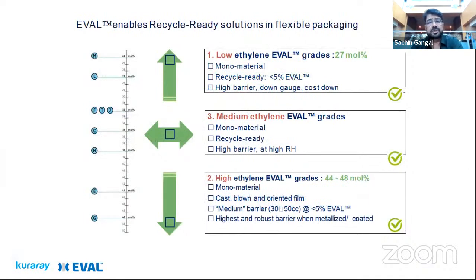We have several EVOH grades based on the ethylene content, where we have the lower ethylene content grades, which can be used to meet the new stringent regulations, where the barrier layer thickness has to be less than 5% of the total layer thickness. We have medium ethylene contents, where again, you require high barrier, probably at high relative humidity. Generally, they are used in combination with, not exactly recycling issue, but in combination with nylon, mainly for meat packaging. You have high ethylene content grades, which are used, as I said, in BOPP structures to give a robust structure and which can be easily metallized and coated. Next slide, please.